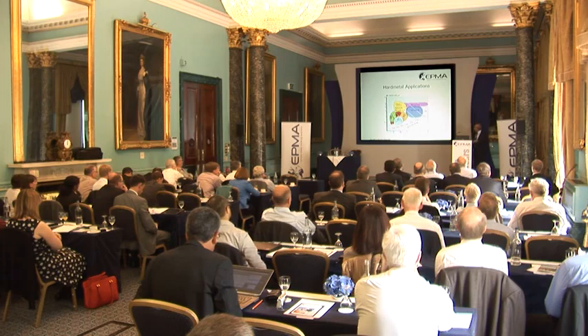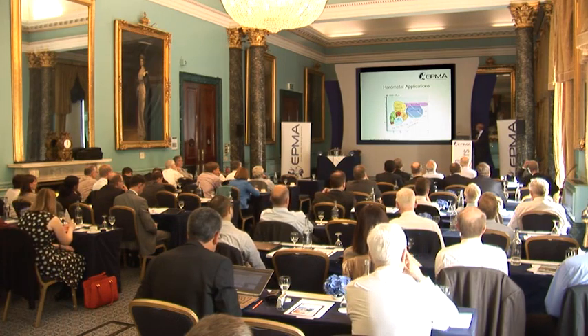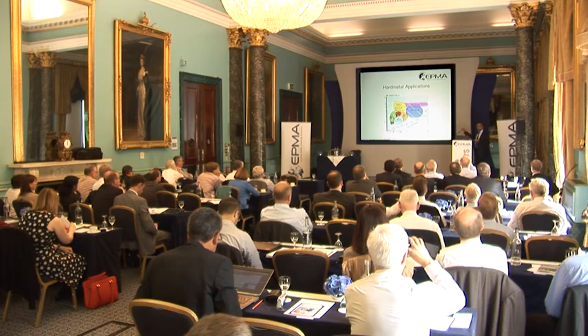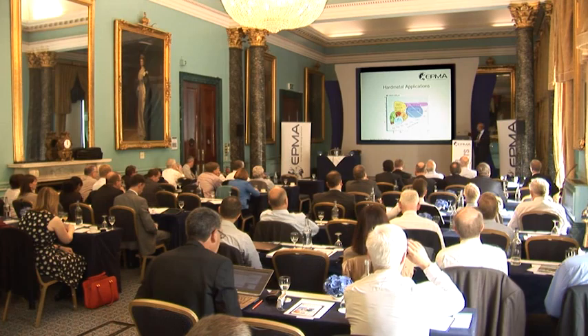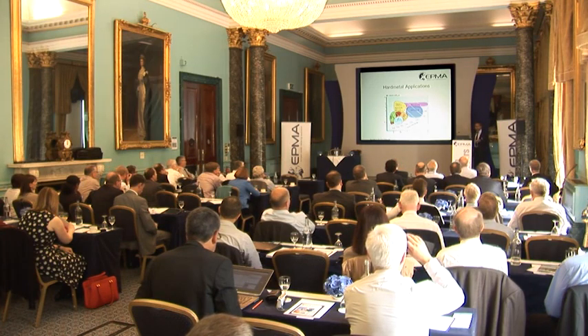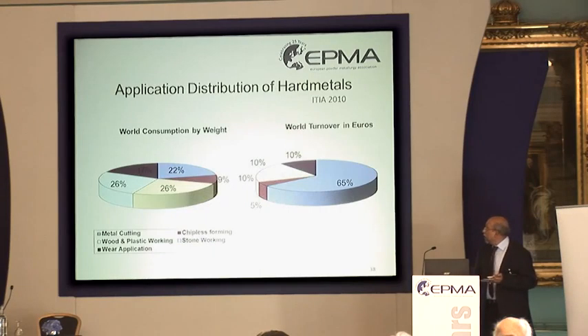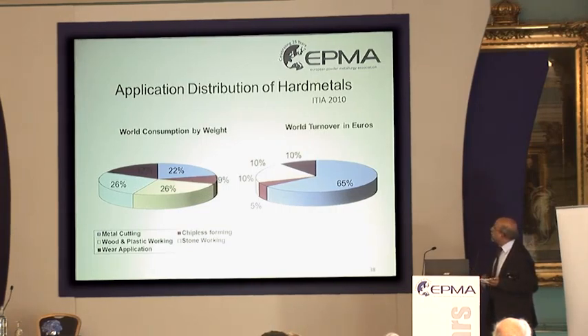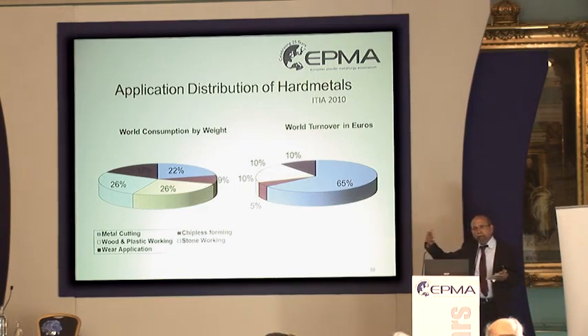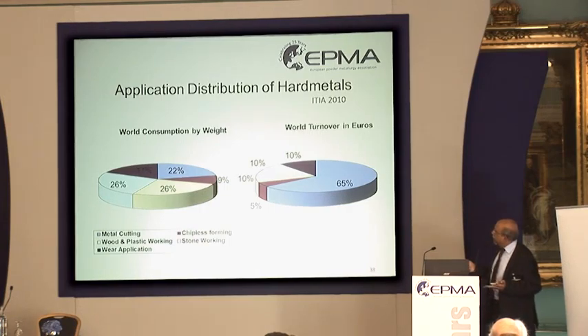And let me move on then to applications. Applications for hard metal are always dependent on the cobalt content and the carbide grain size. And depending on which grain size and cobalt content you choose, you can choose material for different applications. And these applications have been around since the beginning of the use of hard metal. Now, the application distribution of hard metals, according to the data from ITIA from 2010, which is very important: the world consumption by weight for metal cutting is just 22% by weight. And wood cutting is more, and stone working is also more.